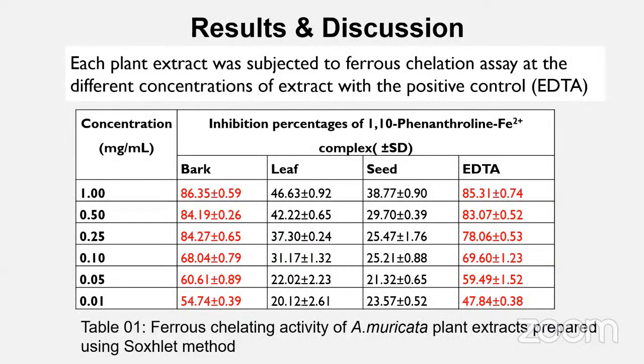These are the results we have obtained in our research study. Here, each plant extract was subjected to the ferrous chelation assay at different concentrations of extract, with EDTA as the positive control. This table shows the ferrous chelating activity of Annona muricata plant extract prepared using the Soxhlet extraction method. According to the results, bark has shown promising activity, higher than EDTA. Marginal activity can be observed with the leaf extract, while the seeds gave weak activity.